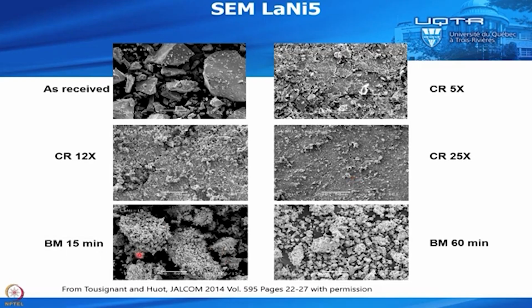And this is ball mill 15 minutes. So you see, as we saw previously, you have agglomeration of smaller particle here, and after 60 minutes, you more or less take these particles and you break them again. So you see the particles are smaller and you have even smaller particle here. Okay.